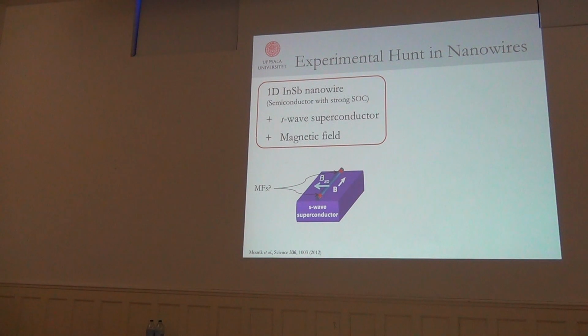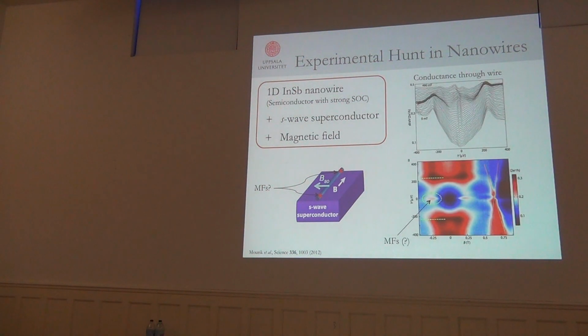And the question is then, theory tells you that you should have Majorana fermions here if the magnetic field is big enough. So this is what they initially measured. This is conductance through the wire going up in magnetic field. For low magnetic fields, there's nothing at 0, but then it looks like there's a peak developing here. The Majorana sits at 0 energy, so it should really give you some signature in conductance at 0 energy. Plotting it in color scale as a function of magnetic field, there's something that pops up here. It doesn't exist at 0 magnetic field because then you're not topological, but it pops up here. So the question is, is this Majorana?